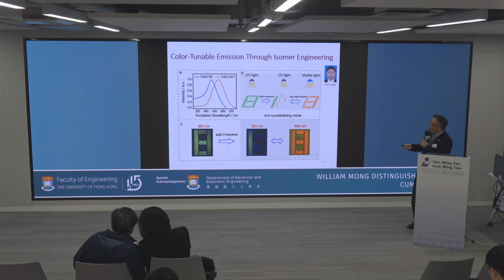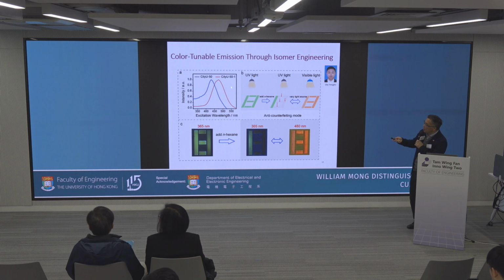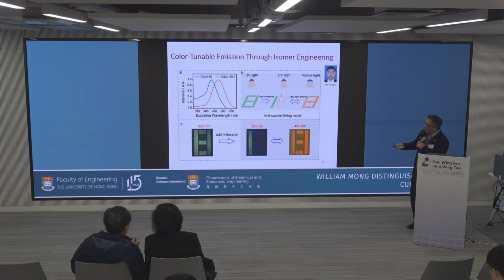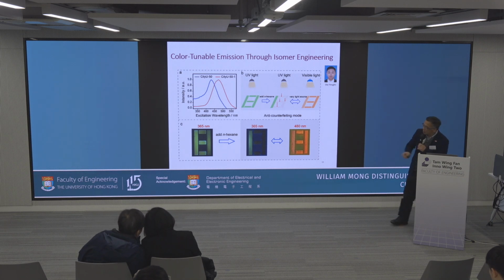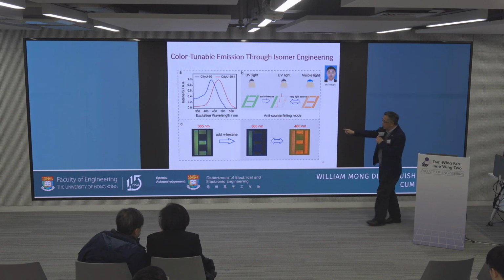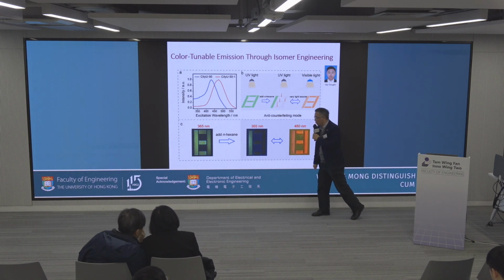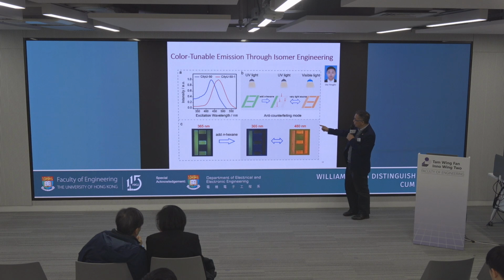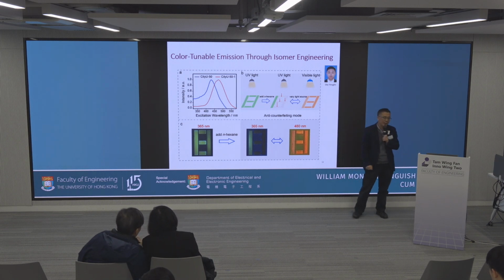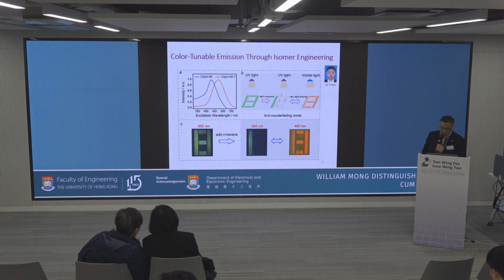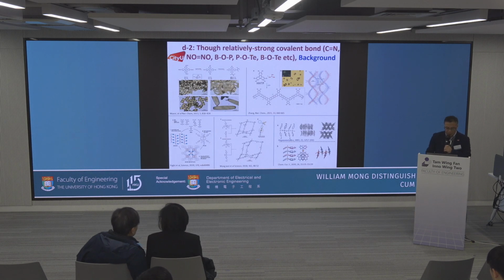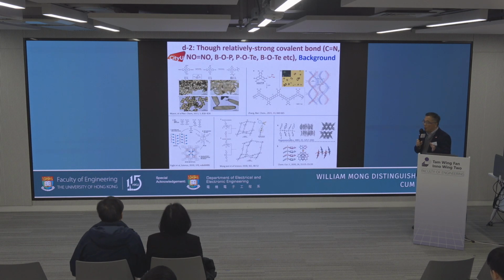We also found that the organic solvent can be replaced by hexane, right? After replacing with hexane, you can see the emission is different. So we make this pattern here, and for the right part, we can use the hexane to do this change. Under the 365 nanometer, we only see the green emission. However, if we use the 480 nanometer to shine, on the right part you can also see the orange emission, okay, as shown here. So that is for the boron dynamic bonding.